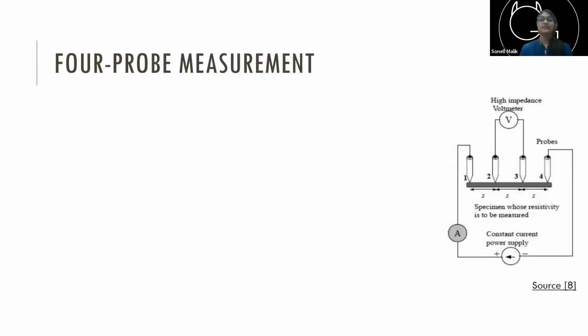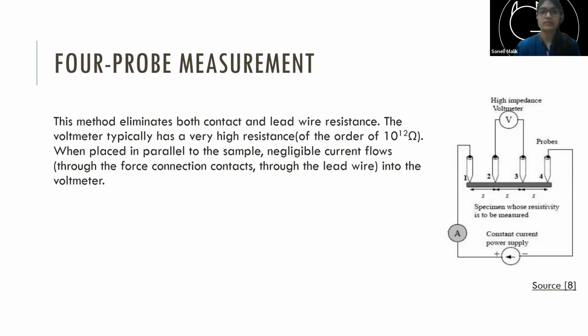Right. So now that we're done with fabrication, how do we measure properties in any system? So electrical measurements, we've all studied the two-probe measurement, where you have one device and you connect probes on two sides, and you use that to supply the current and also to measure the voltage across the sample. Now, in that case, there are two things to look out for. One is contact resistance. So this is my probe. The contact between the probe and my sample will also have some resistance, which will add to the resistance of my sample. And the second is the resistance in this lead wire, the wire that connects to the ammeter and goes through it.